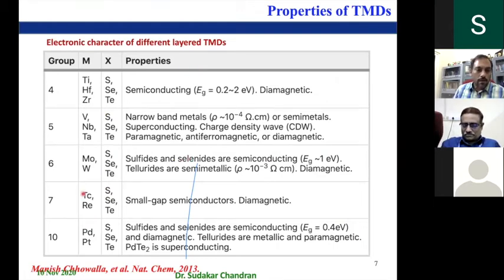So the electronic properties themselves are very interesting in these transition metal dichalcogenides, for example. If you take M and X, the combination of transition metal with chalcogen elements, it can exhibit semiconducting, or it can have narrow band metal or semi-metal characteristics. They are superconducting. But different materials behave differently. Charge density wave quantum materials are known. And then there are materials which exhibit very small gap semiconductors. There are materials superconducting like palladium telluride. So a wide range of properties are possible.